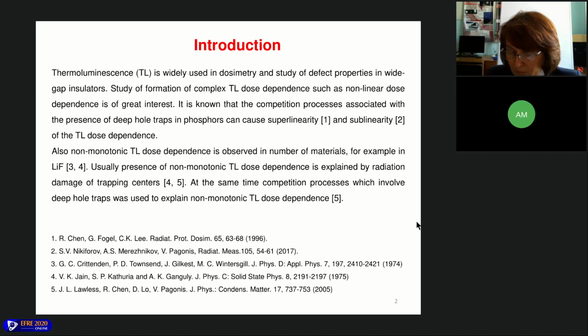It is known that the competition processes associated with the presence of deep hole traps in phosphors can cause nonlinearity of dose dependence. Also, non-monotonic dose dependence is observed in a number of materials, for example, in lithium fluoride. Usually, presence of non-monotonic dose dependency is explained by radiation damage of trapping centers. At the same time, competition processes which involve deep hole traps were used to explain non-monotonic dose dependence.